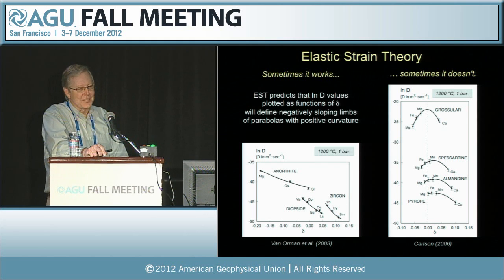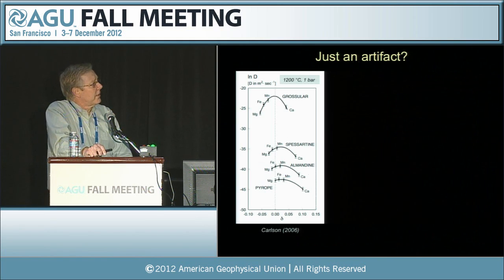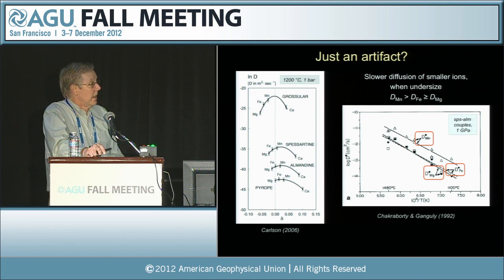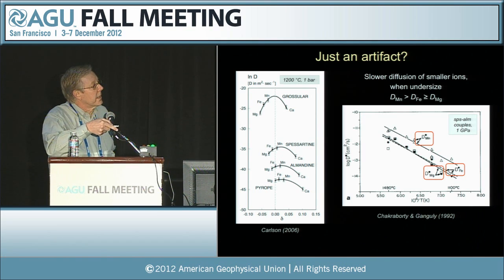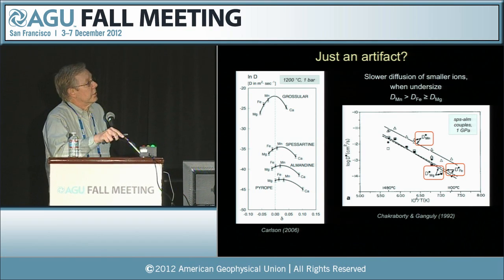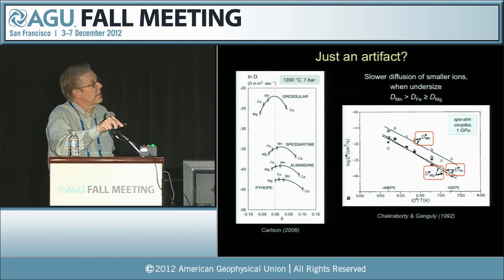And I'm confident that that's not the case, and let me take a minute to address that. These are, after all, just fits to existing data, so we shouldn't be surprised to find in the original data set examples of some of these things. Here's one example from Chakraborty and Ganguly's data that clearly shows slower diffusion for smaller atoms when they are undersized.